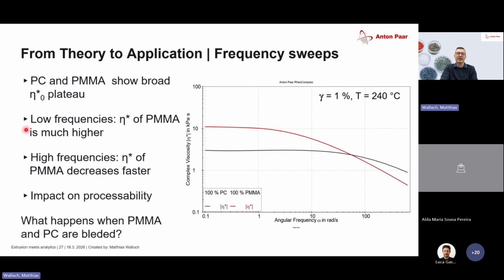I want to give you a nice example. This also points out the importance of rheology compared with the MFR. So we see here two curves. The red one is a PMMA or plexiglass, and the second one, the black one, is polycarbonate. As you can see here, we measured this with an amplitude of 1 and with a temperature of 240 degrees C. And we see a completely different material behavior.